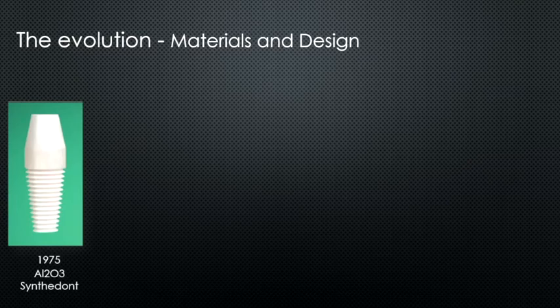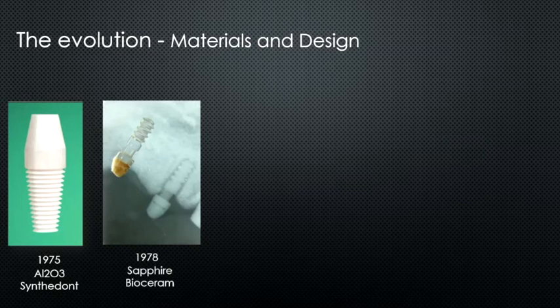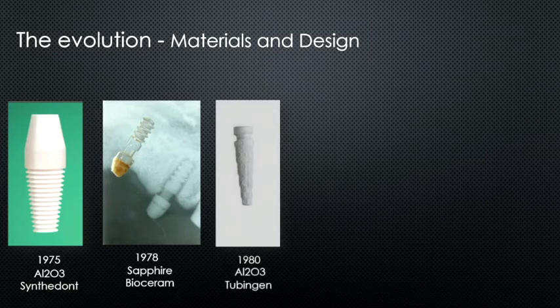So again, it all started with one piece. It always starts with one piece. That's the one I was showing you earlier, the sapphire from Kyocera. Glassy, high failure rate, high fracture rate, because it was just glass. Okay? Then the Tübingen one. But it was still a monocrystal. This also was a monocrystal. But there was a design flaw here. Tons of fracture at the neck there. And the surface at the time was still smooth.